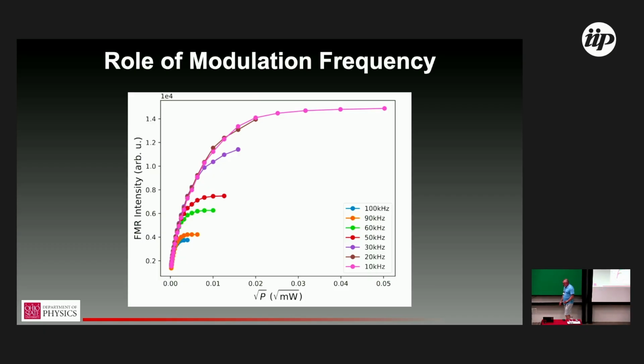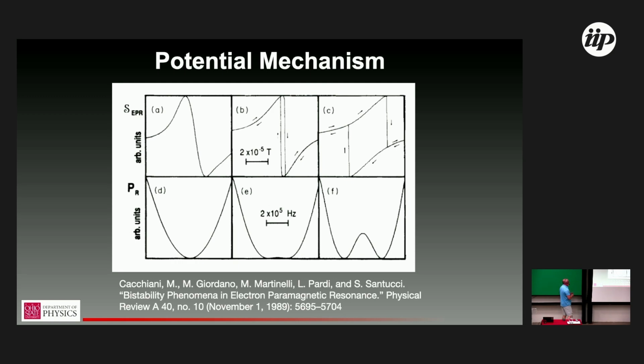And so we were looking for a Suhl instability. We think the systematics are not right for that. Our second guess was, well, maybe there are some paramagnetic spins and we're seeing some sharp feature. We're now pretty convinced it's not that. Some of you may already have thought of this, being more expert than I in magnetic resonance. This is an effect. This is a paper measuring very similar looking data. So we think this is significant in EPR. I think this is anthracite in this paper. At the top is the FMR response, and at the bottom is the reflected power. And the columns represent successive cavity loading.